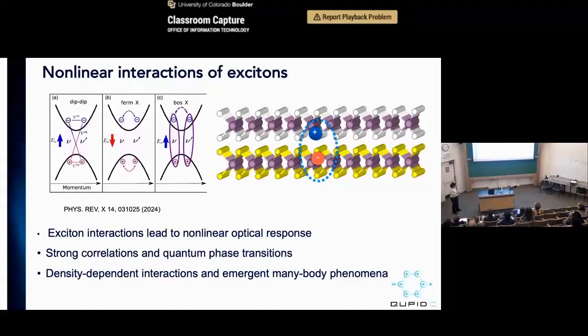And how do two excitons interact? For example, these excitons have an electron and a hole, and they bond together as a pair. So one type of interaction you could have is an exchange-type interaction. For example, you can exchange your electron or your hole, and you can also have exchange of the exciton. So you have this exciton-exciton exchange as well. The exchange interactions tend to be shorter range, so they rely on the overlap of wave functions.